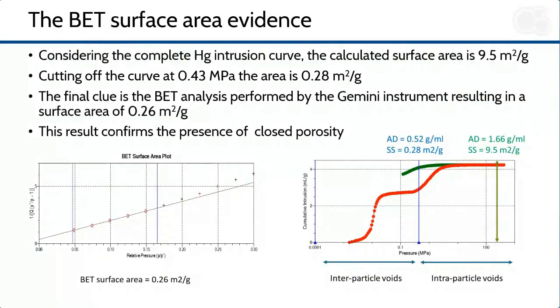Another method to give the right interpretation to mercury intrusion data is to measure the BET surface area using physisorption. Mercury porosimetry uses a very simple geometrical model to calculate the surface area, based on the calculation of the side area of a cylindrical pore with a known volume and access size. In addition, the surface area by mercury porosimetry is strongly affected by possible material compression or collapse. As these effects usually occur at high pressure, meaning small calculated pore size, the resulting surface is very high.